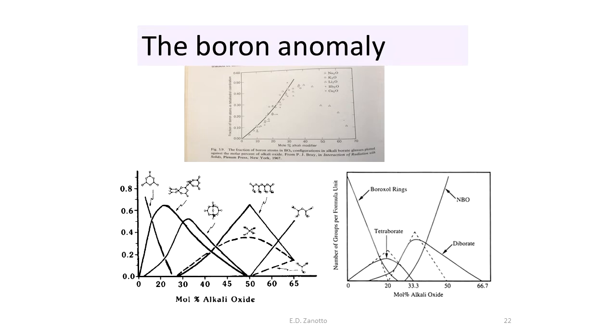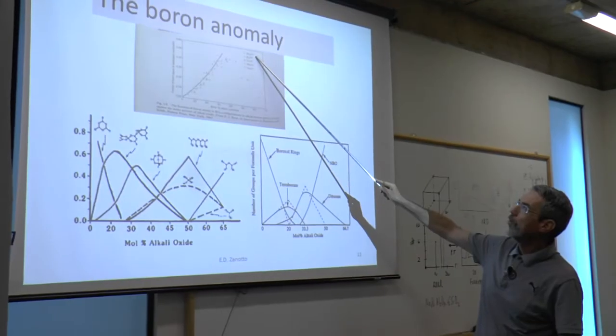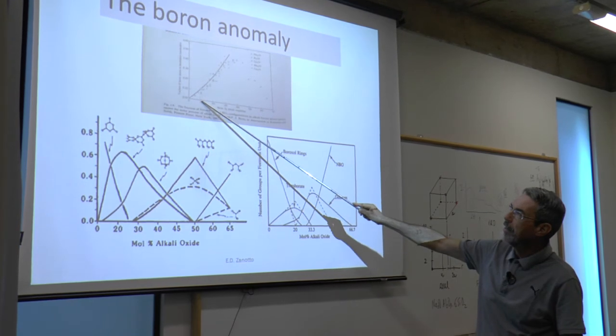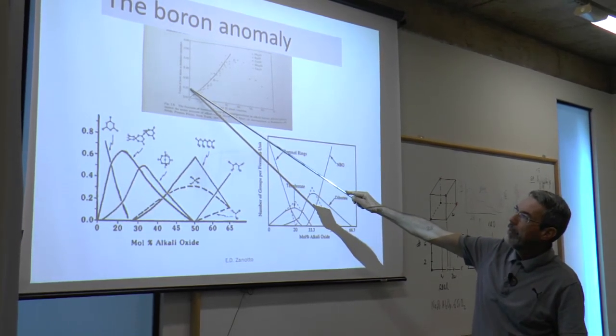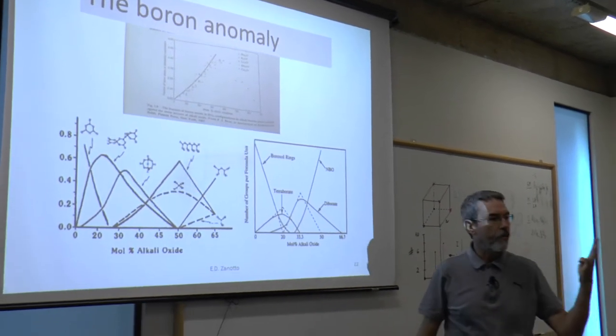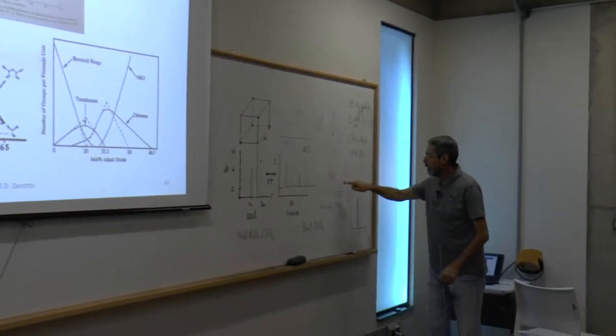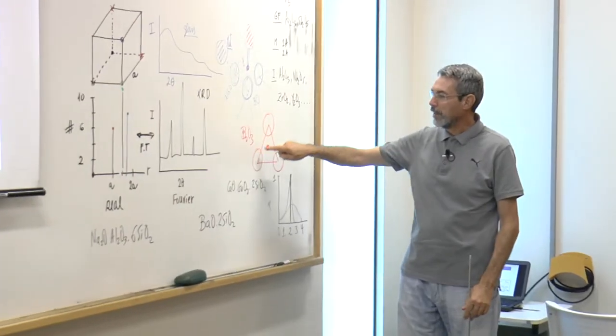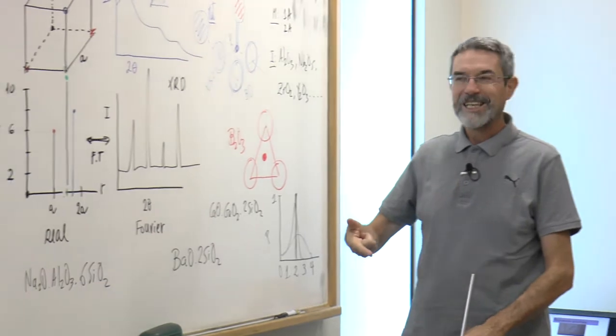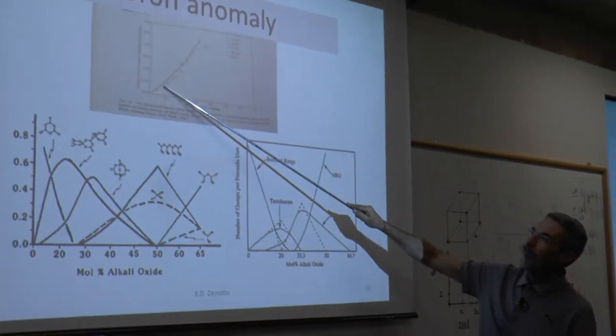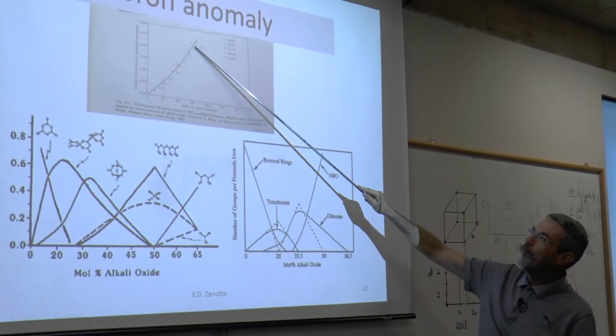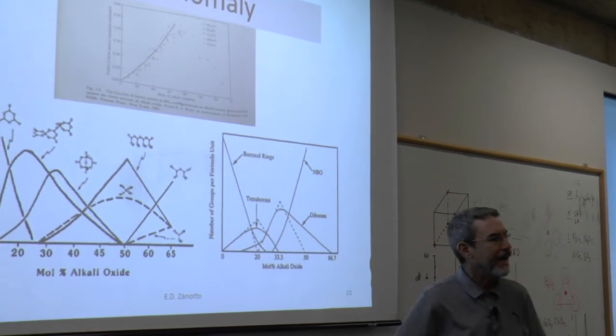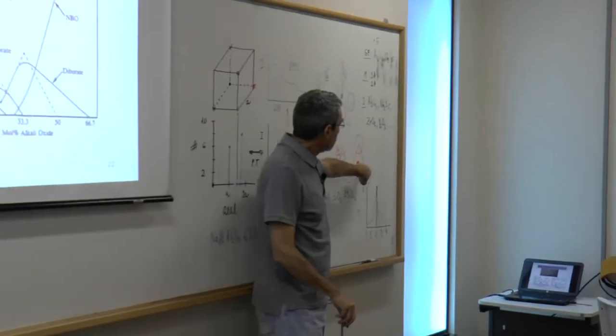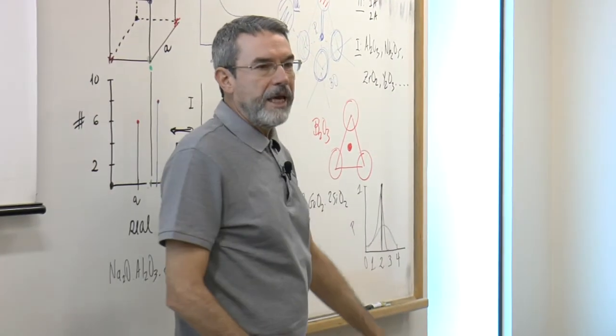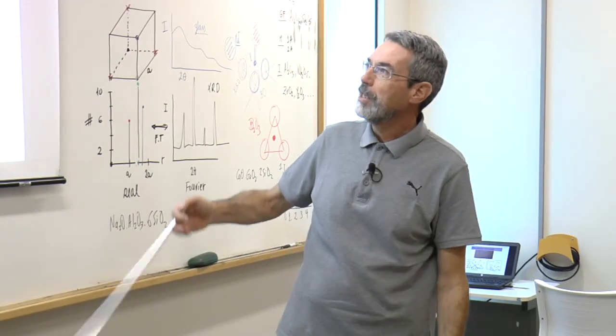With boron oxide it is the opposite. And there's a classical paper showing the fraction of sodium. It's difficult to read, but I tell you, sodium, potassium, lithium, rubidium, and cesium. When you add, say, 10% in mole of one of these, you increase the fraction of boron in coordination 4. Boron normally has coordination 3. Pure boric oxide is coordination 3. But when we add those elements, we increase the fraction of coordination 4, 10, 20, 30, 40, up to 50% or so of all the boron atoms change from 3 to 4, and the properties improve. This is the boron anomaly.